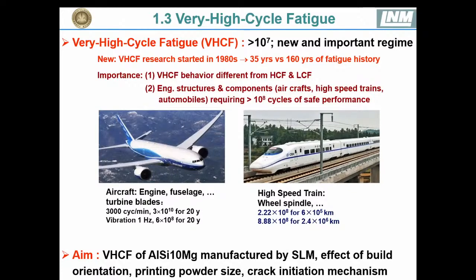So what is very high cycle fatigue? Very high cycle fatigue means the fatigue loading is beyond 10 to the 7th loading cycles. This is a new fatigue research area that can be dated back to the 1980s, and it is important because the mechanism is different from high cycle and low cycle fatigue. Normally the crack starts from the interior rather than the surface. The other important thing is that now a lot of new engineering components and structures, such as aircraft engines, turbine blades, and high-speed trains, are subjected to very high cycle fatigue.